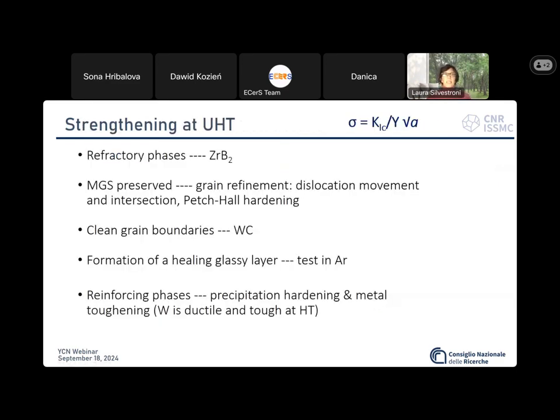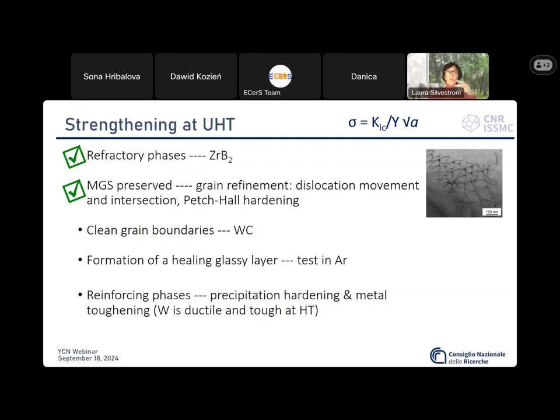To justify the strengthening at ultra-high temperature, we considered Griffith's equation and the attributes that might have changed during the test, acting either on the toughness or on the flaw size, which is actually related to the grain size. We collected a series of positive factors, starting from the refractoriness of the matrix, of course, with the small grain size, which did not increase but actually refined upon loading by dislocation intersection. The grain boundaries were clean, thanks to the choice of tungsten carbide as additive, which cleaned all oxides.